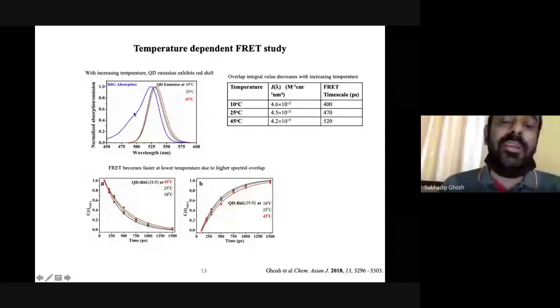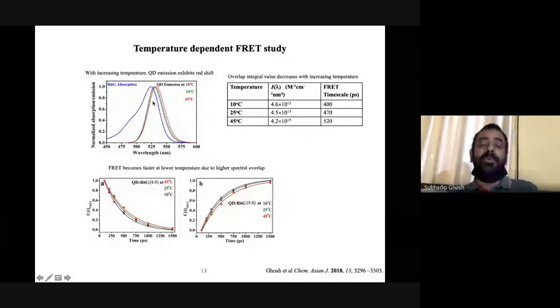Temperature dependence also: if we increase the temperature, we found that the emission peak position of the quantum dot, that is the donor, is shifted to the red side. This is at different temperature. It's showing the emission spectrum of the quantum dot, and this is the absorption spectrum of the quantum dot, and you will find that the extent of overlapping between donor emission and acceptor absorption is decreasing.